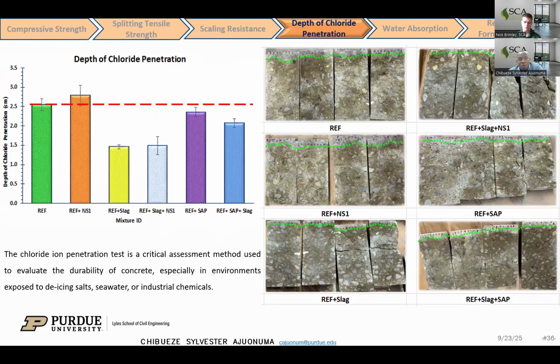And for depth of chloride penetration, after the specimens were extracted and split, we did a profiling, and we found out that the depth of chloride ion penetration was in the range of 1.5 to 2.0 cm, with the reference mix having around 2.5 cm. So using this baseline, we found out that the addition of slag greatly reduced the depth of chloride penetration, signifying an improvement in the microstructure, showing that it resulted in a denser concrete mix.